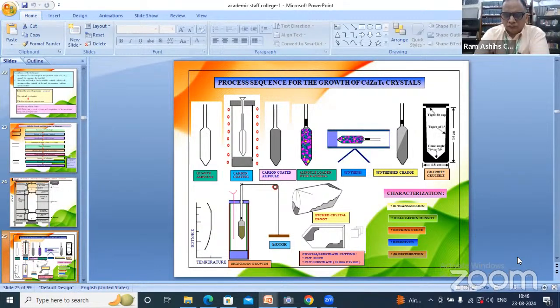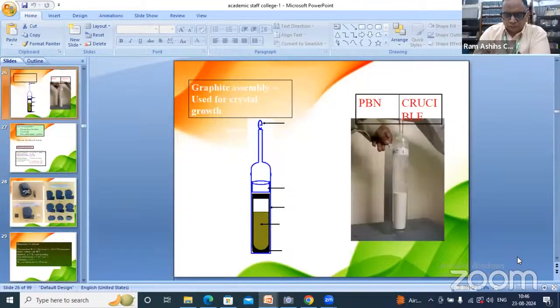After this, we put it in a rocking furnace for 5 days, and after attaining constant temperature, we rock this furnace for mixing the charge. This is the one experiment. We grew this crystal in a quartz ampule and in a graphite crucible, and nowadays we are using a PBN crucible. We were growing in a graphite crucible, but carbon contamination is there. Now the PBN crucible is giving very good results for device purposes.